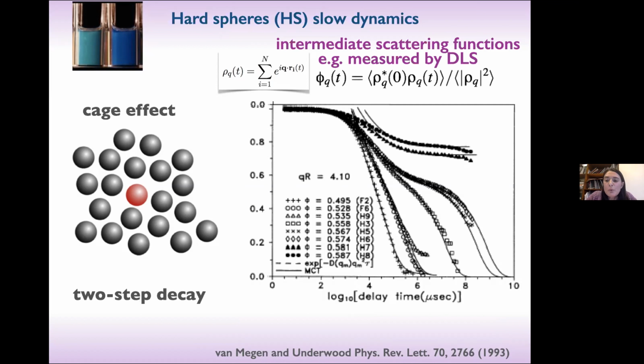But then to diffuse away from the initial configuration, you need some kind of rearrangement of the other particles that allows it to go out from the initial configuration. And the time that the red particle takes to explore this cage becomes longer and longer. You see that here you have a logarithmic time scale, and this is usually what you have to use when you study the glass transition. This time extends by decades until the system arrests on the time scale of the experiment.